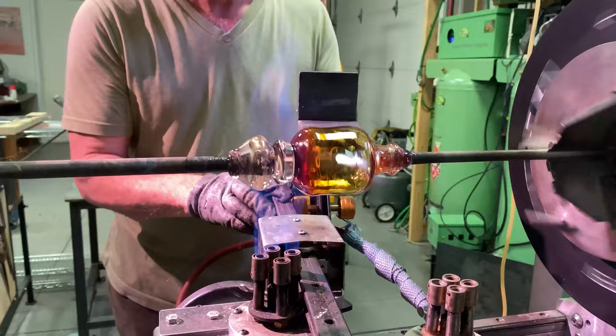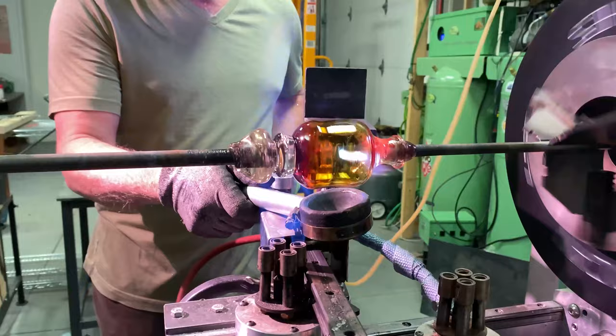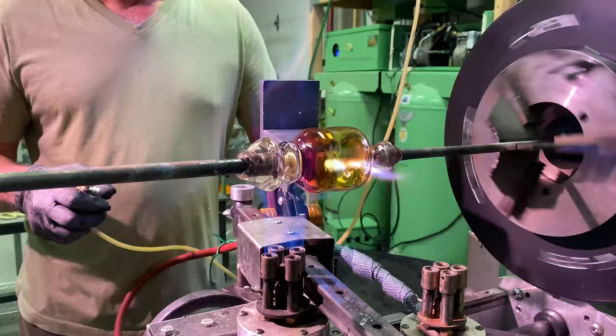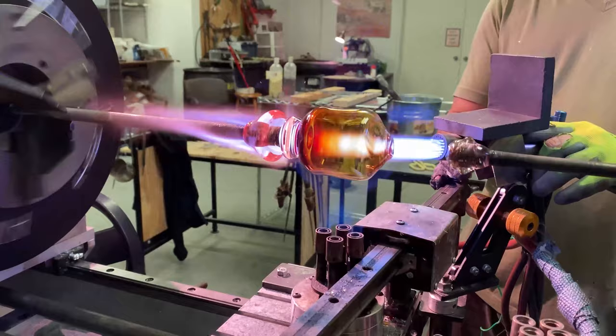And this is more of a scientific, or I guess lathe working, borosilicate technique, obviously, that you're doing here. It is. I'm popping this bubble the way you would in scientific glass, rather than using my jacks to cool it and tapping it. I've done that, but when I work thin like this, it's just very hard to make a crack in thin glass that doesn't travel down a bit. And this is just much easier.